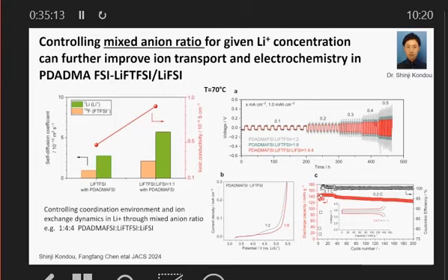And again, if you look at the symmetric cell testing, the red values represent the truly mixed anion, the 1 to 4 to 4, and the green one represents the 1 to 8 of the FTFSI, and the 1 to 2, which is the maximum conductivity in the system, is the grey. So despite having the maximum conductivity, that's not the best performer in terms of the lithium symmetric cell overpotential and the stability. You see that, in fact, the lower conductivity but the high transport number gives you the better performance in this particular case. And you can also see the stability is increasing between 1:2 and 1:8.